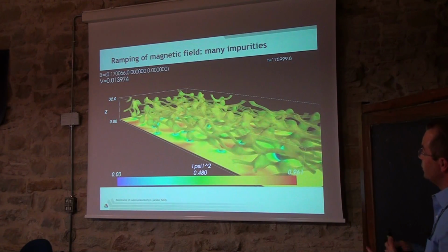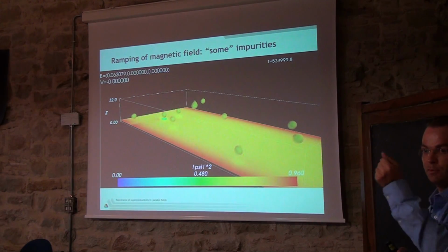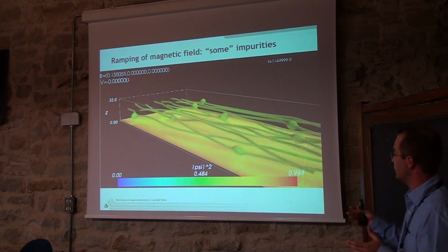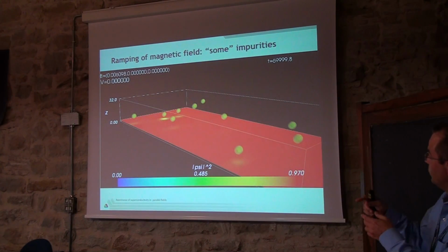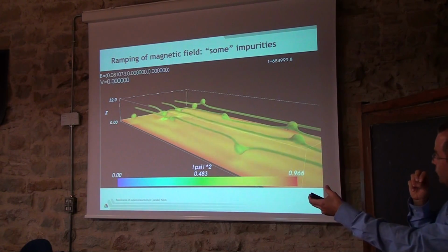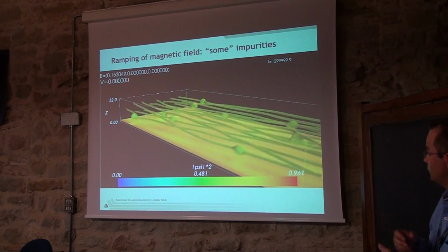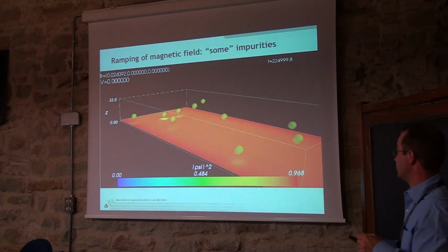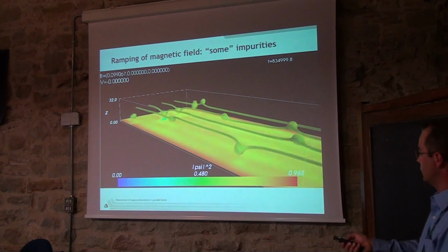So then we needed some mechanism to bend vortices a little bit so we have an effective Lorentz force in it. So we added only a few of them. And then suddenly we saw something very interesting. So now we increase the magnetic field, and at intermediate values you actually see some motion, and then if you further increase the field, you see that the additional vortices basically stabilize this motion again, and basically you are back into the non-dissipative state.